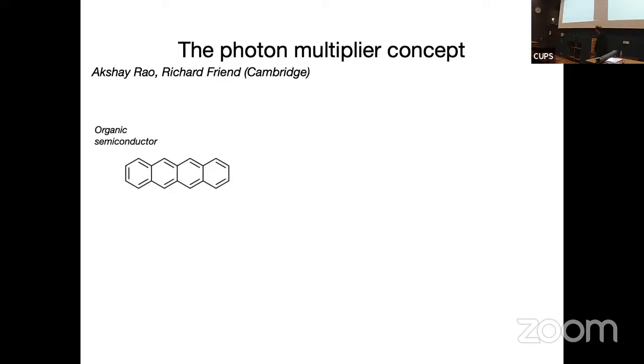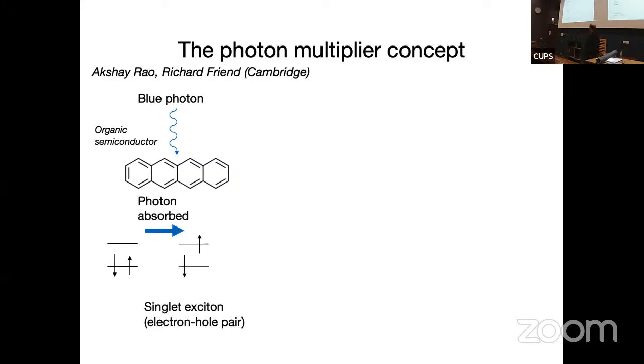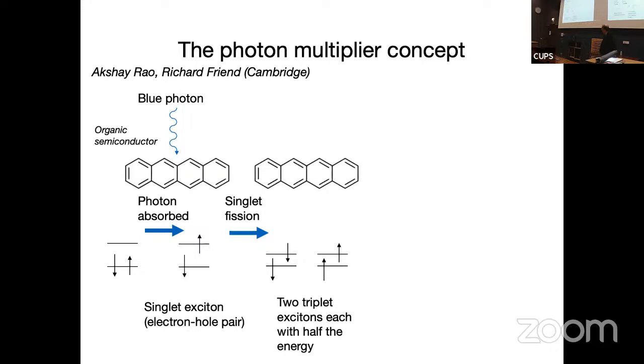If you imagine an organic semiconductor, so it's a bunch of benzene rings stuck together, basically. If you get a blue photon, it comes in, it's absorbed, it makes an electron hole pair, and this will be a singlet. So the electron and hole will have opposite spins. Now, due to some subtleties that can happen in these organic semiconductors, in the right material, these singlets can split into two triplet excitons that each has half the energy.